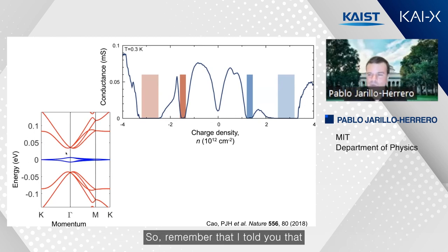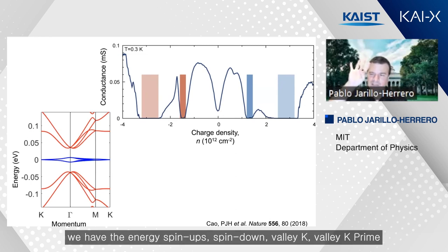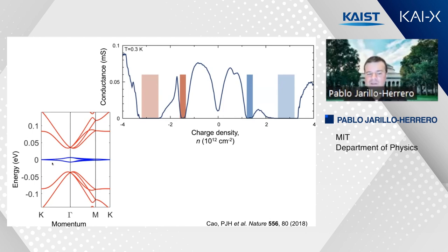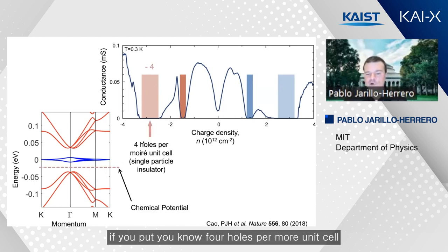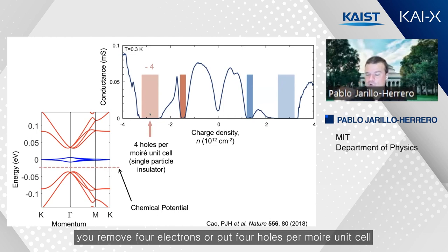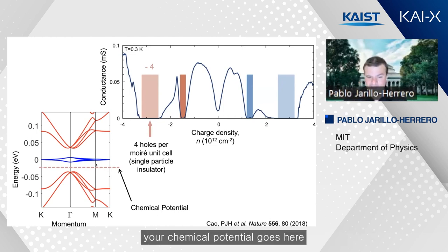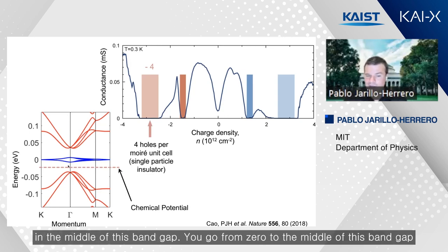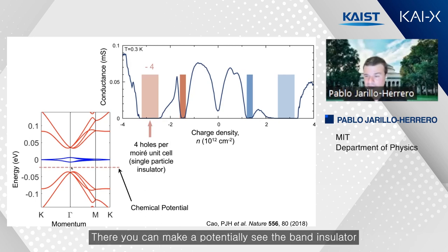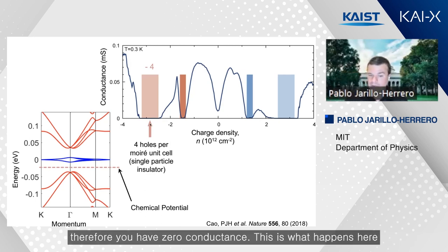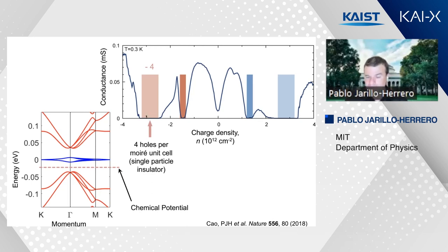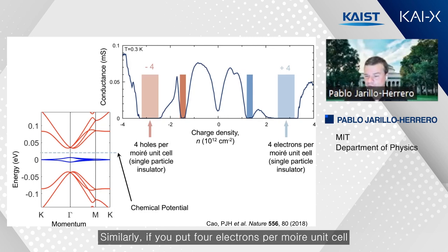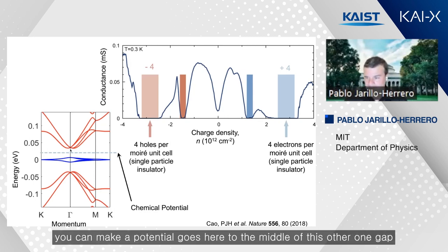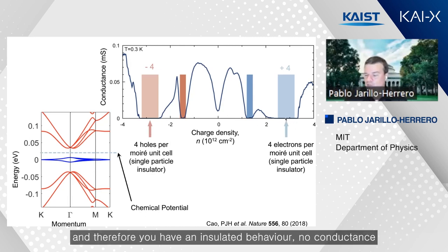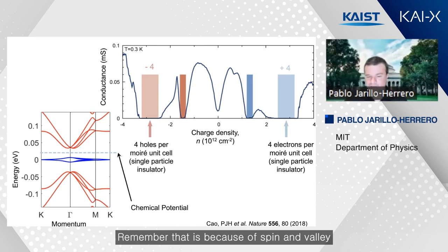So remember that I told you that we have a fourfold degeneracy: spin up, spin down, valley K, K prime. Turns out, if you put four holes per moiré unit cell, starting from charge neutrality, from zero, you remove four electrons or put four holes per moiré unit cell, your chemical potential goes here in the middle of this band gap. There, your chemical potential is in a band insulator, therefore you have zero conductance. This is what happens here. Similarly, if you put four electrons per moiré unit cell, your chemical potential goes here to the middle of this other band gap, and therefore you have insulating behavior, no conductance. Remember that that four is because of spin and valley.